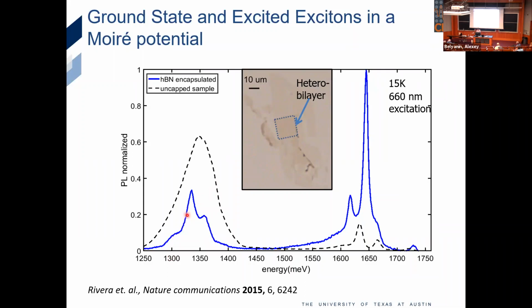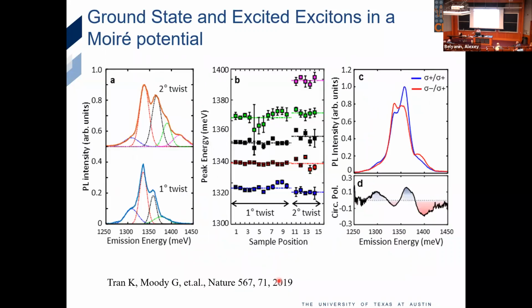We start to see fine structures underneath these broad resonances. We didn't know how to interpret them until my hardworking students made a dozen of them. We start to see trends. So this is a Moiré superlattice with 1 degree. This is a Moiré superlattice with 2 degrees. We're only looking at the interlayer exciton right now, so these are low energy transitions. We measure them at many different points on the sample. As you can see, there's still some fluctuations. There are still some bubbles and wrinkles.